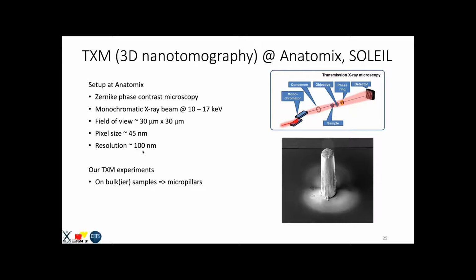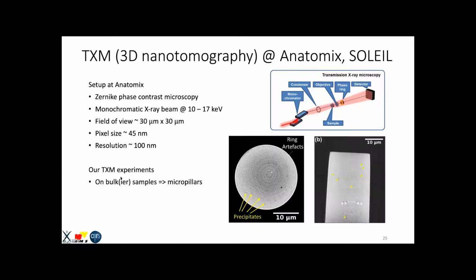So what we did is we made bulkier samples than TEM lamellae. So we made these micropillars and we studied them with TXM. So here is this typical image that you would get out for this micropillar. You will have these ring artifacts that are forming, but you can clearly see the precipitates that are forming over here. These ring artifacts, we can remove them with post-processing treatment.